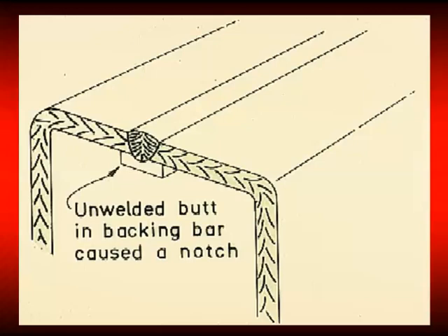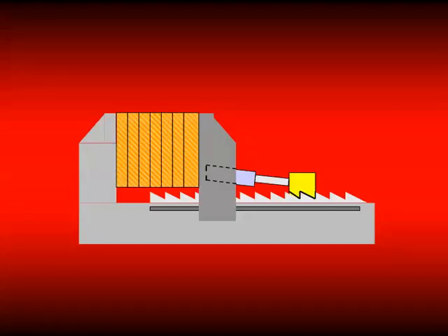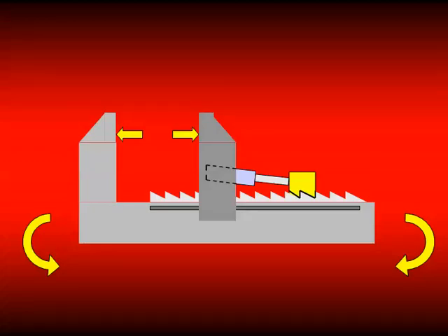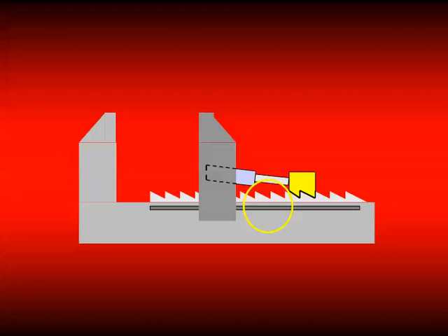in two. This is a company in Florida that makes big presses to glue together laminated wood arches. So here we see the plies of wood that are being glued together, and this is the hydraulic cylinder. There's a dog that fits into a rack. Now what we need to know is we have a beam that's subject to a bending load when it's loaded up. And now we're going to look at the detail connecting the rack to the beam, and sure enough, there's a crack that's developed into the beam because there's a tack weld or a weld between segments of the rack.